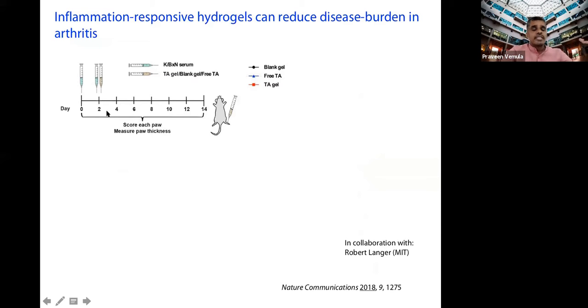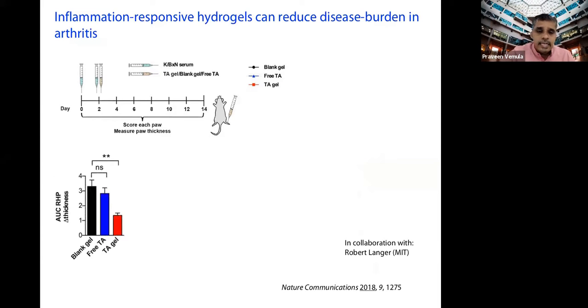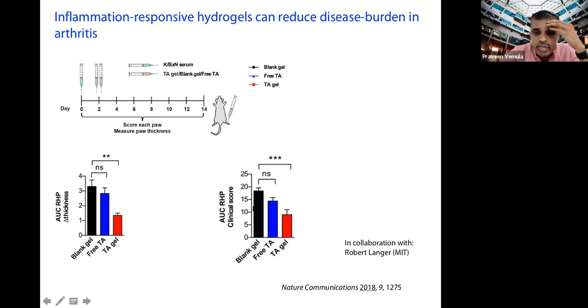Again, we induced the disease, and then 2 types of injections were given. One, either free drug was given without encapsulating into the gels, and the same dose of drug was encapsulated in the gel and given. If you measure the overall therapeutic outcome, one way to measure is the swelling of the paw, right? Less swelling means better treatment. As you can see, the drug in the gel has a much better therapeutic outcome compared to the same dose of drug given freely. And you see the same trend with the clinical score as well, right?